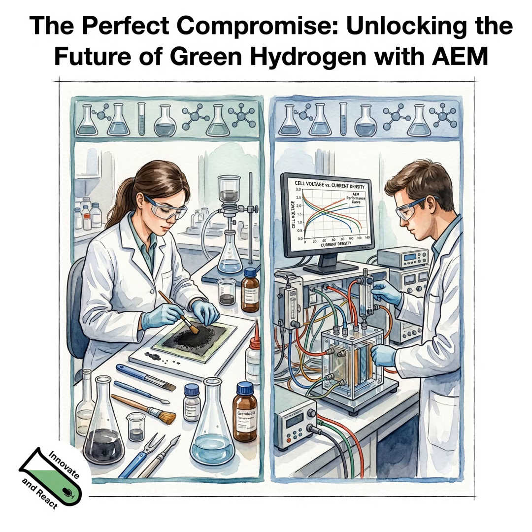But if they degrade, then it is more prone that your catalyst really moves out of the system. Okay. And apparently it shouldn't be the same ionomer for the catalyst layer as for the membrane, as people find out that there are different surrounding conditions that govern more or less degradation. So it's not too easy at the moment. Even if you have a normally stable ionomer for the alkaline world, manufacturing it so that it's even more stable for the catalyst world is another challenge in and of itself. No, and they are not really on the market right now. There are some that are claimed to be, but it's only for the catalyst layer, and it's far less than those who just do the membranes. Mm-hmm.